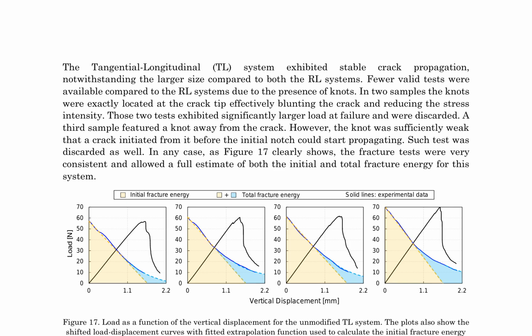The tangential-longitudinal (TL) system demonstrated stable crack propagation, despite being larger in size compared to the radial-longitudinal (RL) systems. However, the presence of knots reduced the number of valid tests, with 2 samples discarded due to knots located at the crack tip, which effectively blunted the crack and reduced the stress intensity, resulting in significantly larger loads at failure. A third sample with a knot away from the crack was also discarded, as the knot initiated a crack before the initial notch could start propagating.